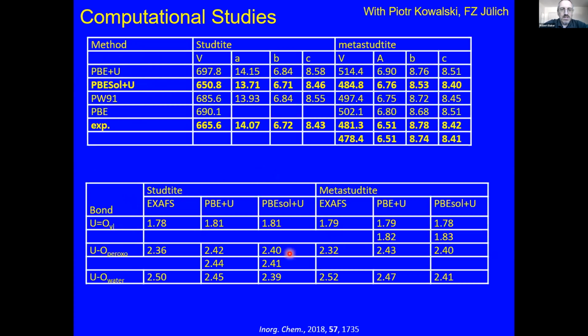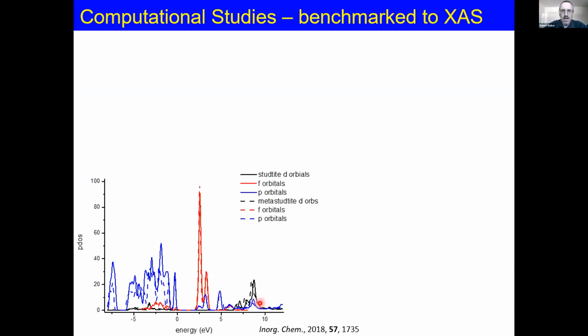So one of the problems with this is that the bond lengths are not quite as reproducible as the electronic structure, but this is a limitation of the technique. But even so, we do seem to get pretty good fits with the NEXAFS data. These are the DFT density of states plots, and we can already see in red the f orbital contributions, which look very similar to our M-edge spectra.